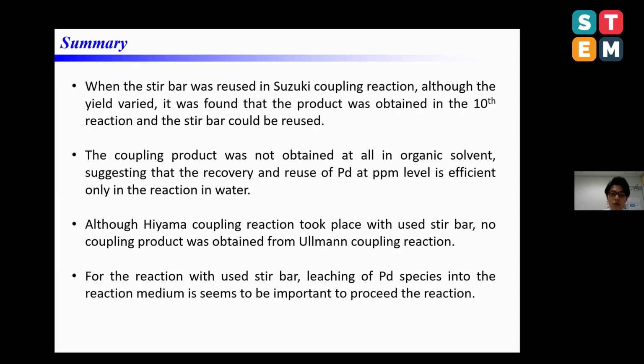The coupling product was not obtained at all in organic solvent, suggesting that the recovery and reuse of palladium at ppm level is efficient only in the reaction in water. Although Hiyama coupling reaction took place with used stir bar, no coupling product was obtained from Ullmann coupling reaction. For the reaction with used stir bar, leaching of palladium species into the reaction medium seems to be important to proceed the reaction.